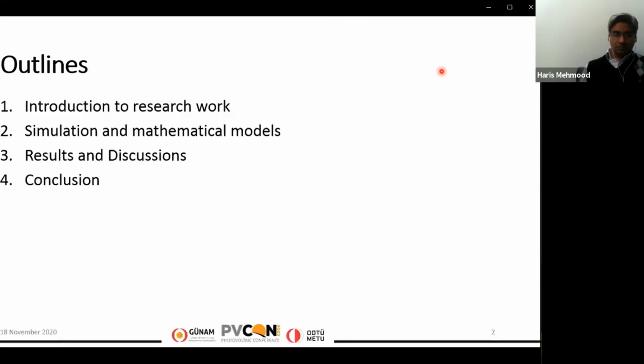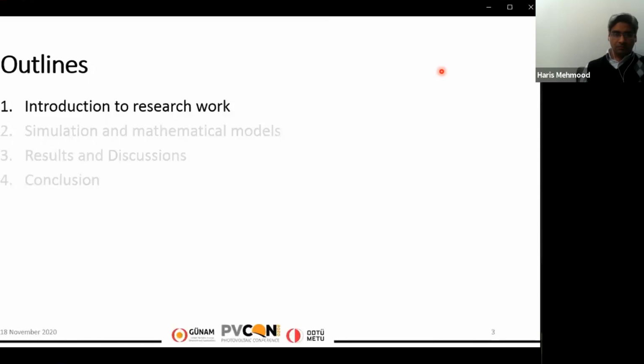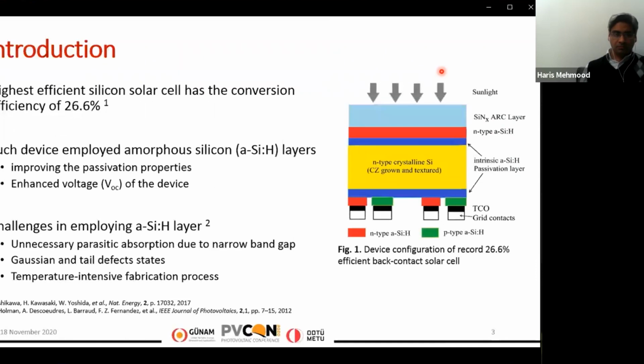So here is the outline of my research presentation. Starting with the introduction to my research work, the literature advertises that the highest efficiency silicon solar cell has a conversion efficiency of 26.6%. That is based on the structure of the interdigitated back contact silicon heterojunction solar cell, IBC SHJ structure. In this type of solar cell, both sides of the silicon wafer are passivated with amorphous silicon, and the top side is capped with an n-type amorphous silicon layer, and the bottom side is capped with n-type amorphous silicon and p-type amorphous silicon in a patterned fashion.